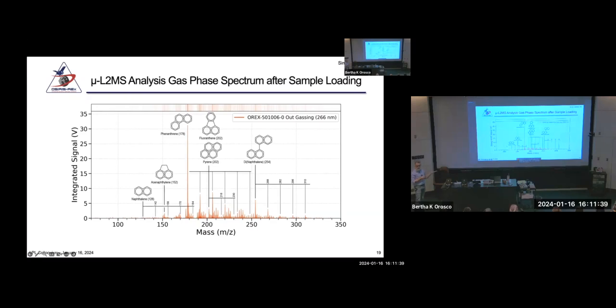Without even firing the laser, the sample is outgassing. All these different peaks are different organic molecules that are just coming off a freshly fractured surface from the sample. These are all what we would call polycyclic aromatic hydrocarbons. An aromatic hydrocarbon is one that has this six-sided ring here. If it's a single ring, it's benzene. And then when you have two, you get naphthalene, phenanthrene when you get three, pyrene when you get four. So Bennu has a lot of these native organic aromatic hydrocarbons that appear to be loosely bound and easily liberated from the material just by exposure of a new, fresh surface in vacuum.